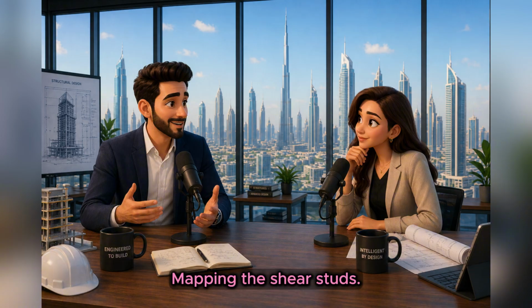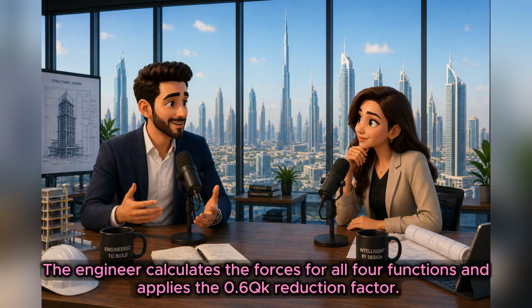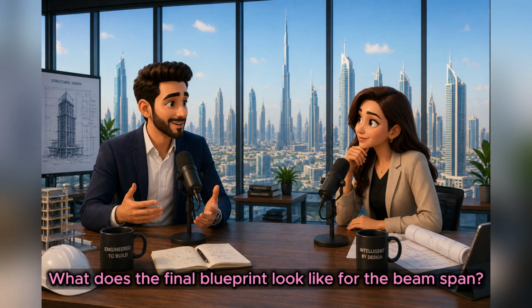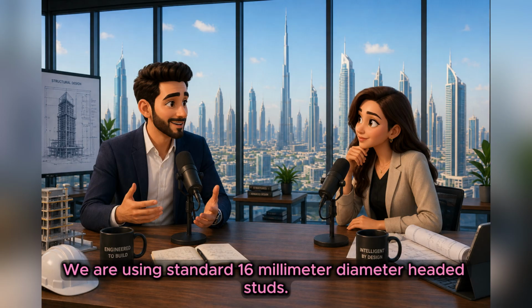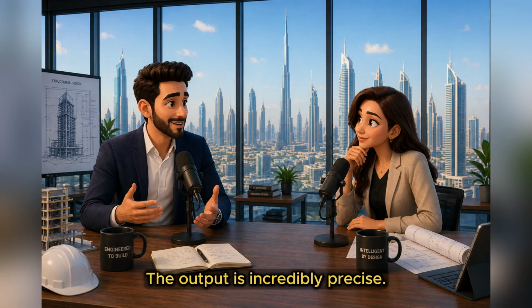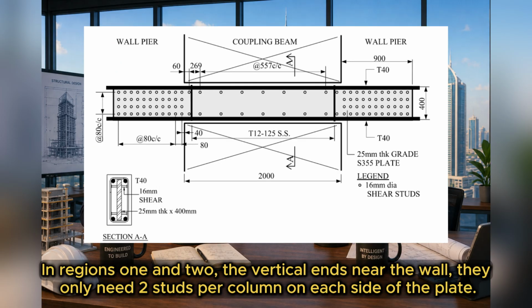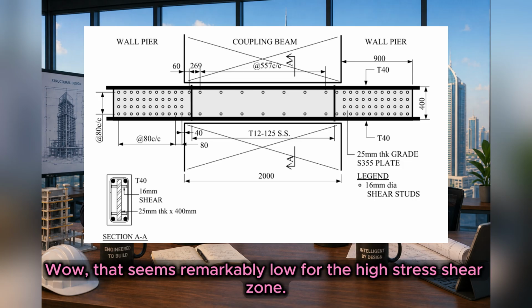Step 3. Mapping the shear studs. The engineer calculates the forces for all 4 regions and applies the 0.6 Qk reduction factor. What does the final blueprint look like for the beam span? We are using standard 16 millimeter diameter headed studs. The output is incredibly precise. In regions 1 and 2, the vertical ends near the wall, they only need 2 studs per column on each side of the plate. Wow, that seems remarkably low for the high-stress shear zone.